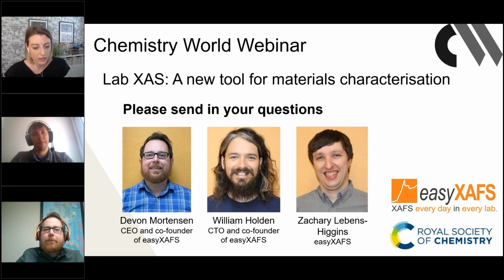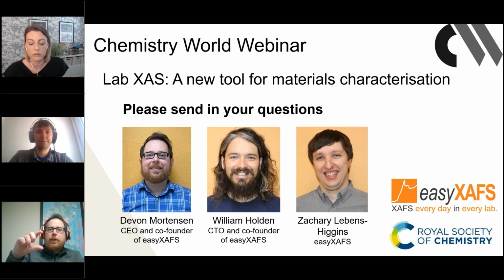Okay, that's good. I'm just seeing a question from Joyce, and I think you just answered it. It was how small should the powder samples be? I think you mentioned a couple of milligrams. Was that correct? Yeah, that's how much of the material. As far as the actual area that you're probing, we're very narrow in one direction, at 50 microns, and then tall in the vertical direction, about a centimeter. You can aperture that down if you have a smaller sample, or you would just like to look at a smaller area of your sample. That can be done just by placing an upstream aperture. Okay.